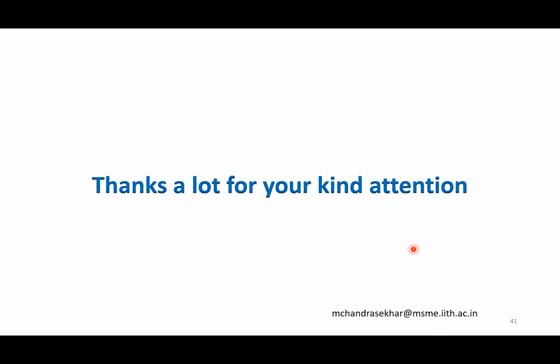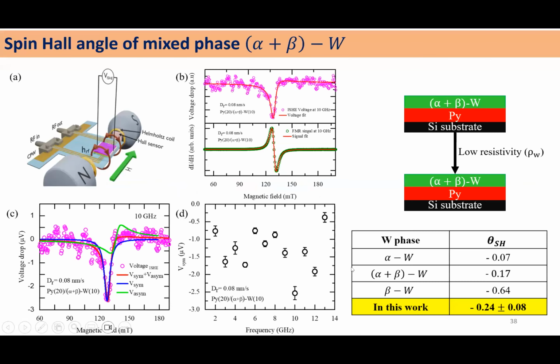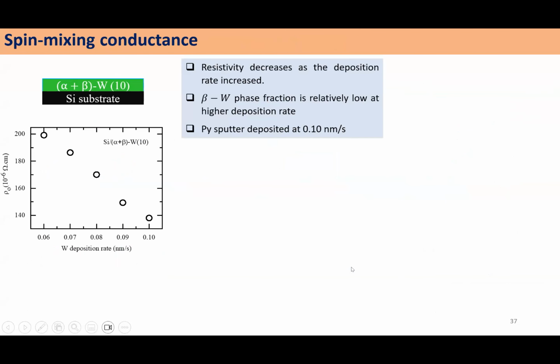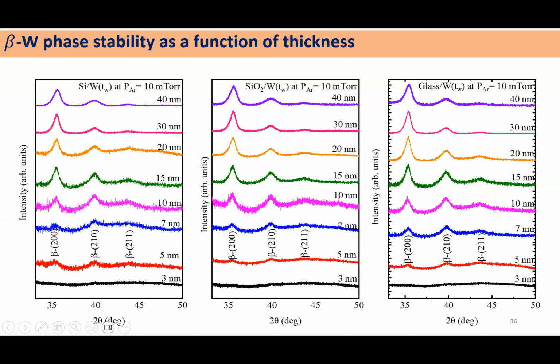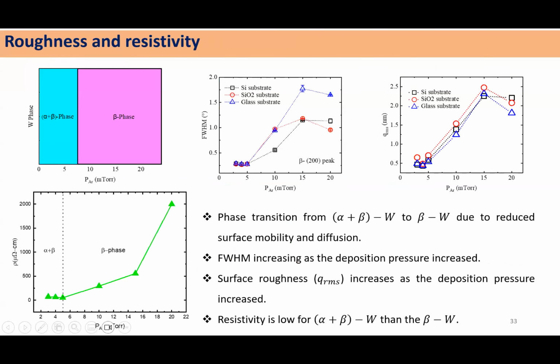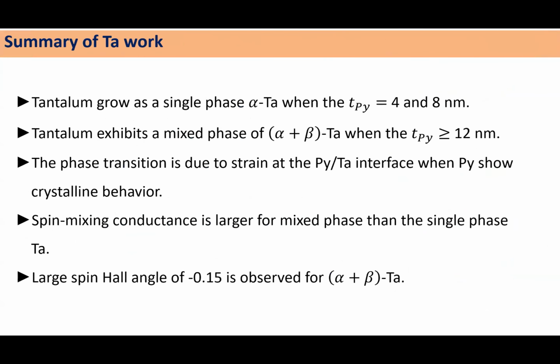I'm curious about the estimation of the spin Hall angle as you have shown from the spin pumping measurement. There you have the ISHE spectra, which has some asymmetry in it. When we do ST-FMR also, we get a symmetric component. It's not purely asymmetric. So could you clarify how you are separating the spin rectification?